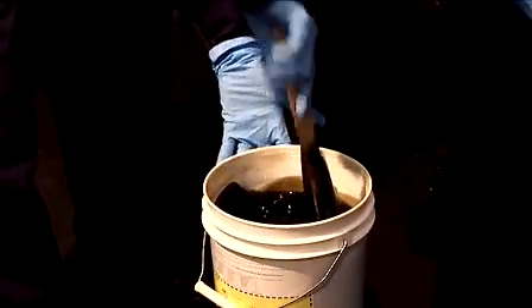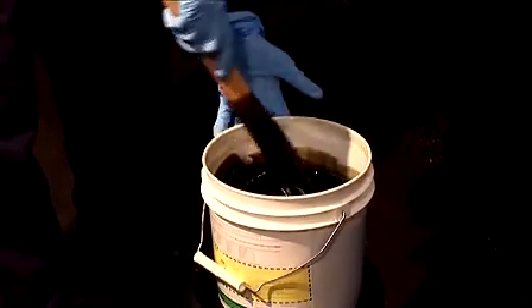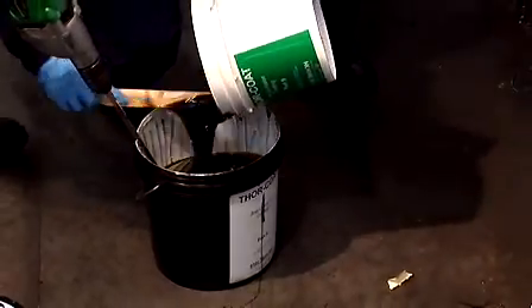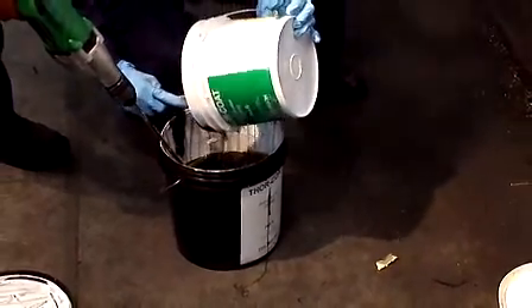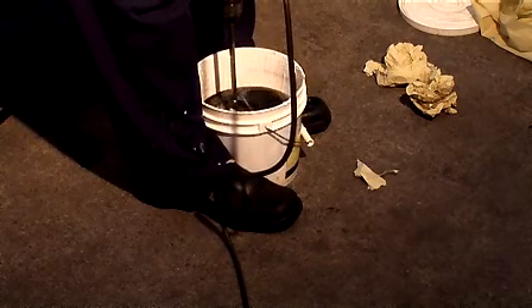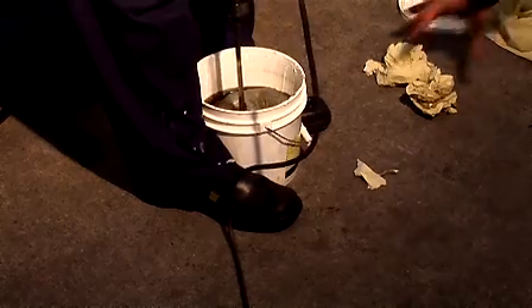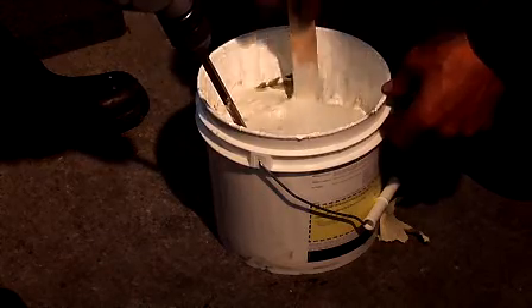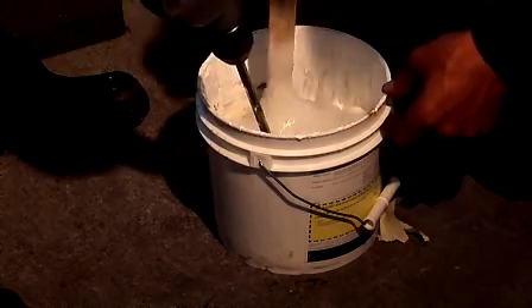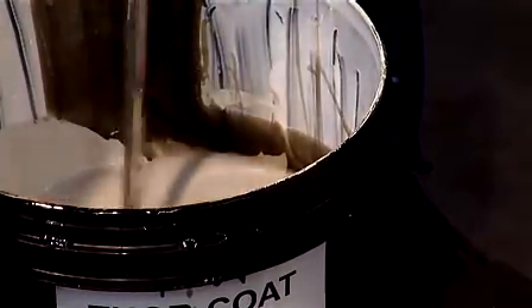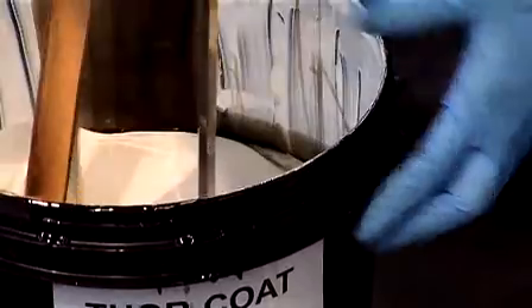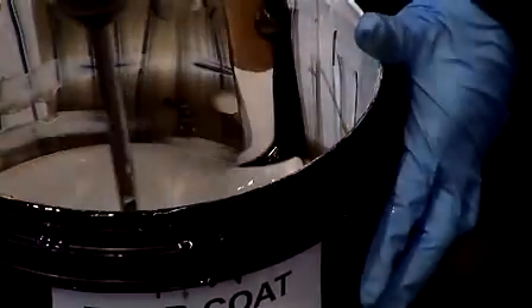Mix each component separately before blending using a power mixer for Part A and manual mixing for Part B. When both elements have been thoroughly mixed, add the entire quantity of Part B, the hardener, to Part A, the resin. Use the power mixer at slow speed to thoroughly blend the 2 components, ensuring that the mixer reaches all locations within the container. Note that Thor Coat must be applied within 45 minutes of mixing and is most easily handled within 20 minutes. If more than 1 kit is required to cover large areas, mix and apply each kit as needed. Do not mix several kits at the same time.